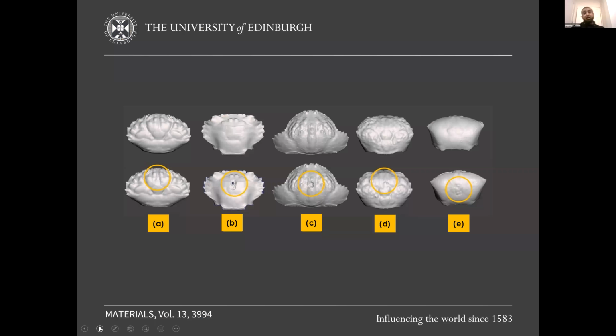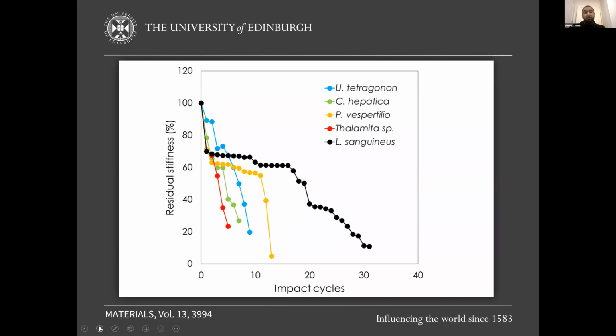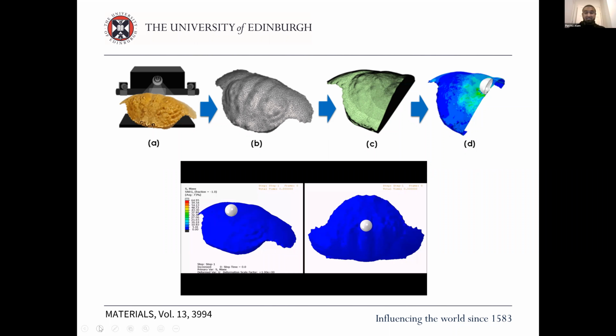Anyhow, importantly, the crab shells do fail in very different ways. Some of them are more brittle and some of them tend to show more ductile denting characteristics. And you can see that iterated again here through this graph. You've got L. sanguineus and P. vespertilio that show ductile characteristics. We've got the residual stiffness here plotted against the number of impact cycles, whereas the other 3 crab shells seem to be quite brittle in their cyclic failure character. So in order to better understand how shape affects, or potentially could affect, the failure mechanisms, I asked my PhD student Gabrielis to basically run some impact simulations on the 3D scans we had of these crabs, and we got quite a lot of interesting data out of that.